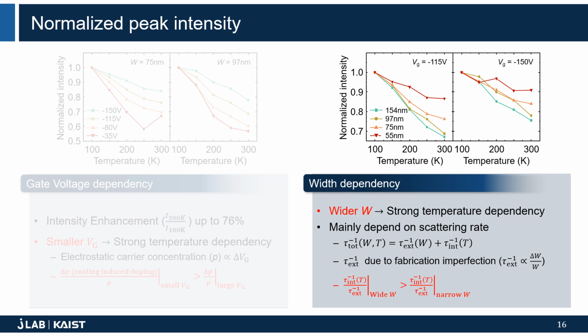The important point here is that, assuming the same amount of fabrication imperfection occurs regardless of the resonator width, a sample with a narrow resonator width has a large width variation. Then, in the same manner, the narrower one has a larger contribution to the temperature-independent extrinsic scattering rate. So, the wider nanoresonator sample has stronger temperature dependency than the narrow one.